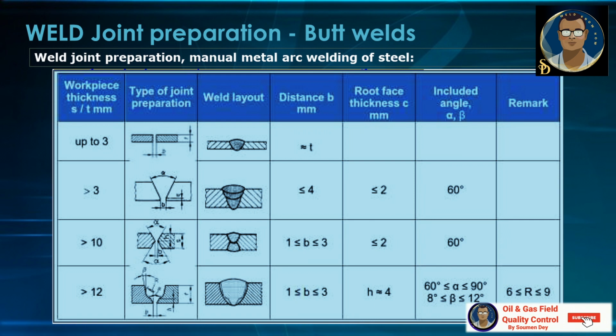If it is greater than 10 mm, then if there is access from both sides of the welding, we will prefer double V welding for better penetration and very good heat distribution. So here also the included angle will be preferred 60 degree. The root face will be less than or equal to 2 mm. And the root gap will be 1 mm to 3 mm.